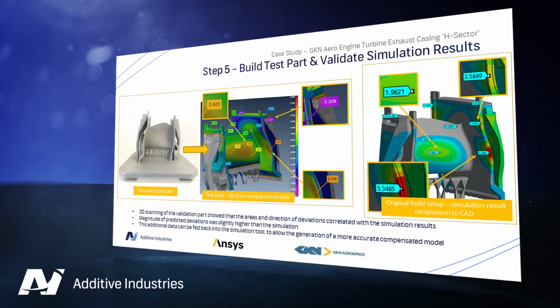The distortion was found to be negligible and localized to one corner of the plate. The part was 3D scanned using a Romer arm laser scanner, and the surface profile compared to the nominal CAD geometry using a best fit function.